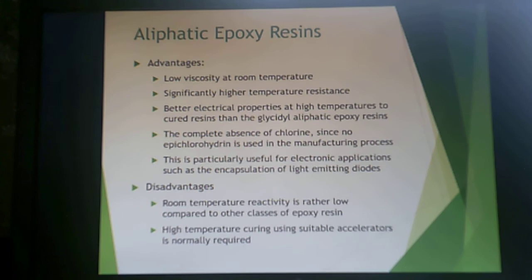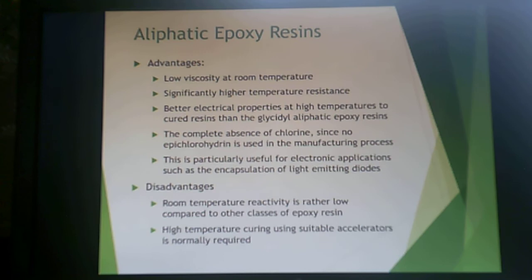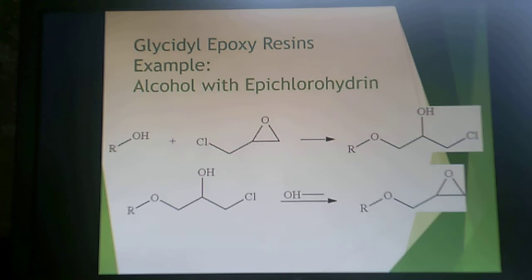The advantages of aliphatic epoxy resins include low viscosity at room temperature, significantly higher temperature resistance than aromatic epoxy resins, better electrical properties at high temperature compared to glycidyl aliphatic epoxy resins, and the absence of chlorine since they don't use epichlorohydrin — which is useful for electronic applications such as LED encapsulation. The disadvantage is that room temperature reactivity is rather low compared to other epoxy classes, typically requiring high-temperature curing with suitable accelerators.